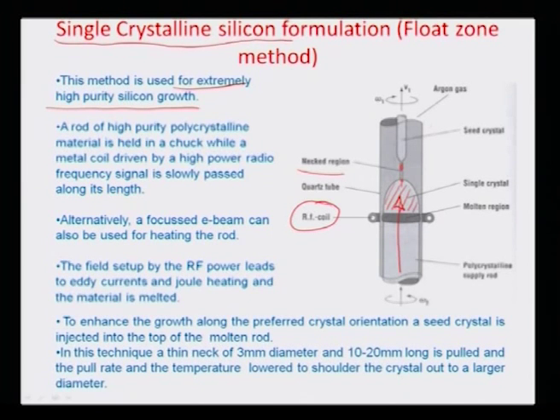orifice. Both the feeding rod as well as the wafers are moving at certain omega velocities. And one good advantage here is the uniform heating. So there are very few thermal stresses, and as such no thermal stress related dislocations, which is otherwise the case in Czochralski's method, where there is a huge thermal gradient available because it is essentially a contact mode heating. Here most of the heating means are RF based, so that it is non-contact mediated, and there are no thermal dislocations whatsoever in the crystal. So that is another method of formation of single crystalline silicon, known as the float zone method.